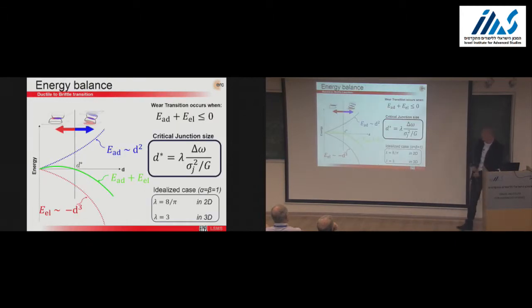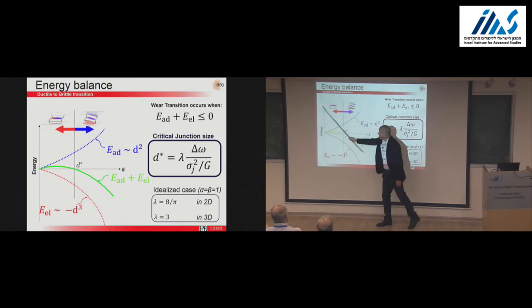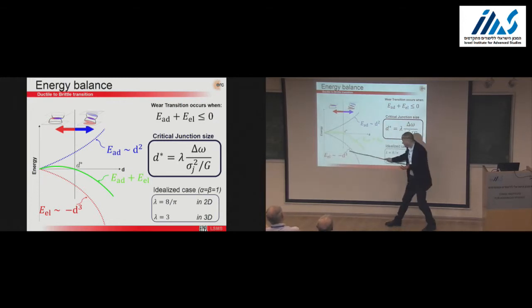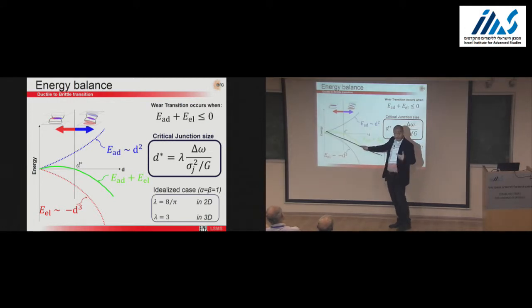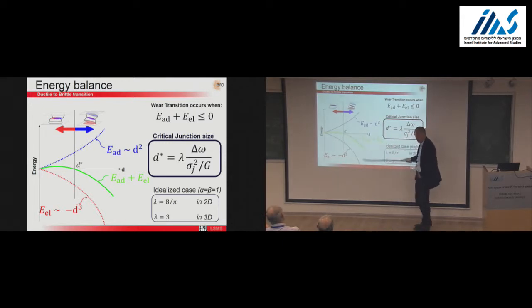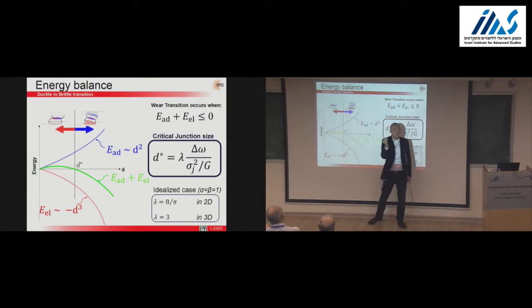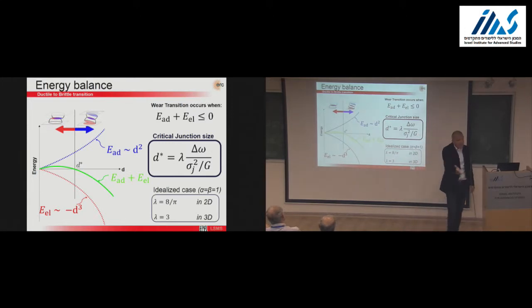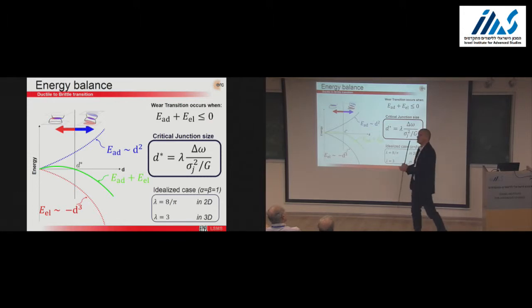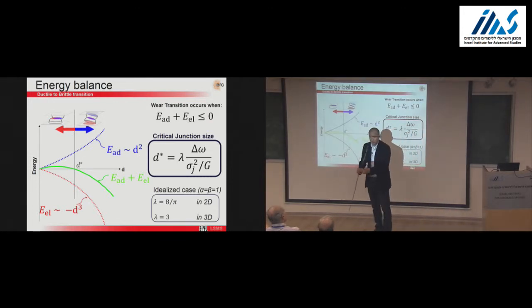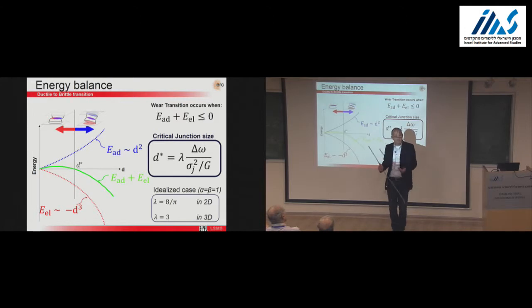So if we look at how those energy terms change with the size of the junction. So this is D, the size of the junction, and this is the energy terms. My budget at the bank is the elastic energy. It scales with D cube. The price to pay to grow surfaces scales with D square. If I add those two curves, I get this green line, okay, that crosses over at a critical length scale D star. So below D star, we should expect that we do not have enough elastic energy. We should expect a smooth wear process. Above D star, we have enough budget, and we can grow cracks.